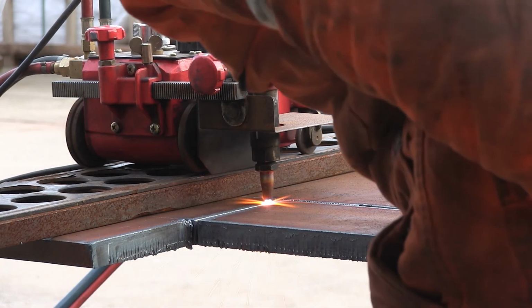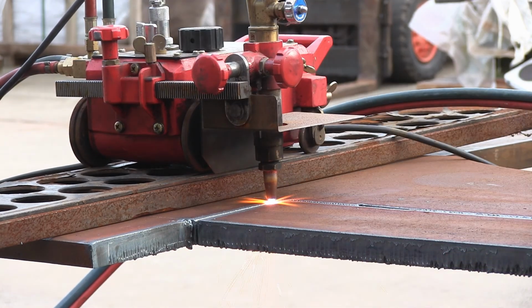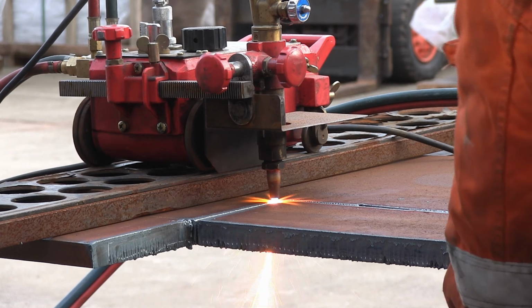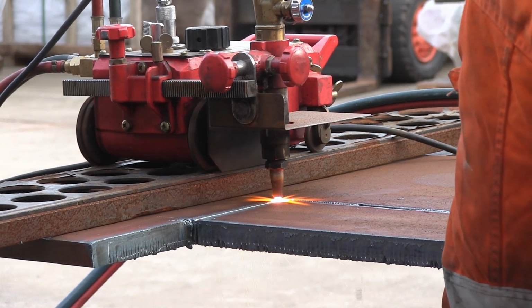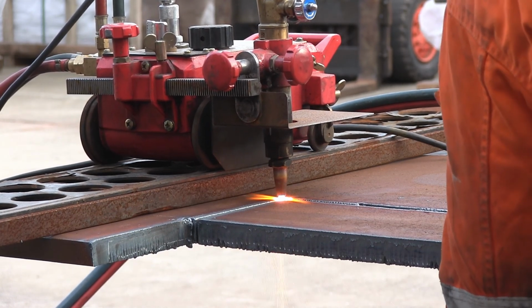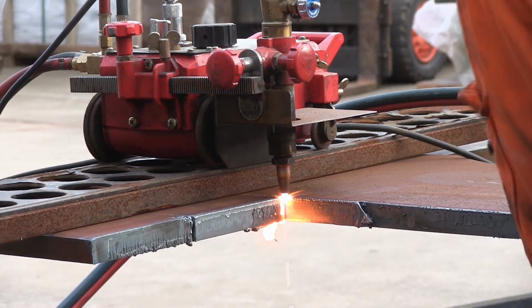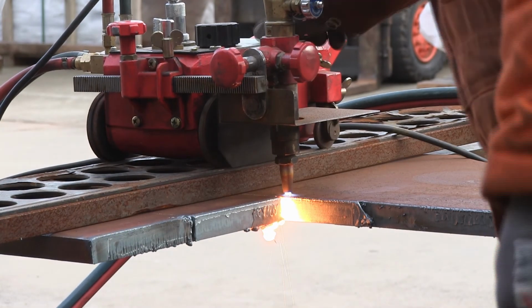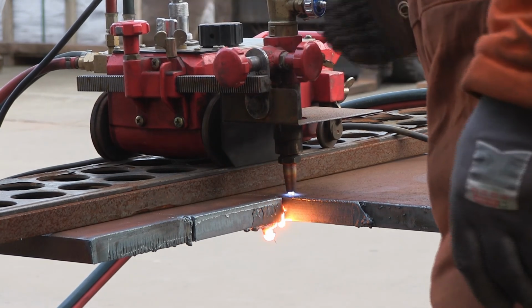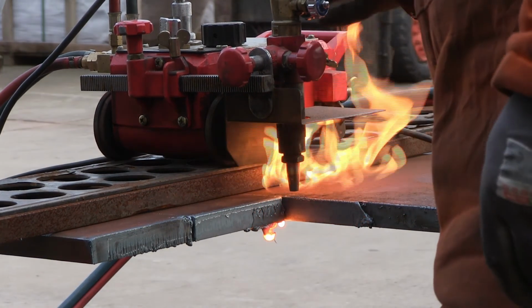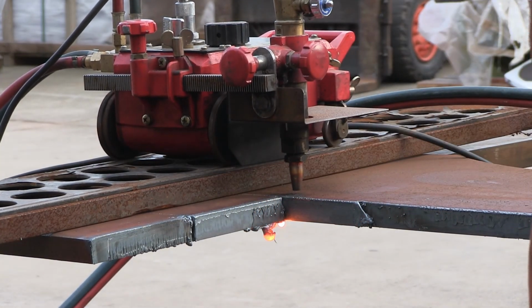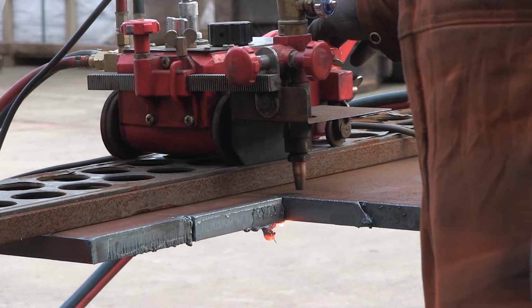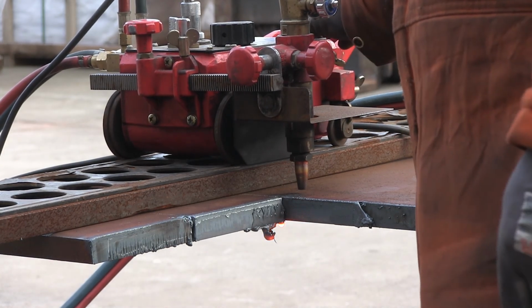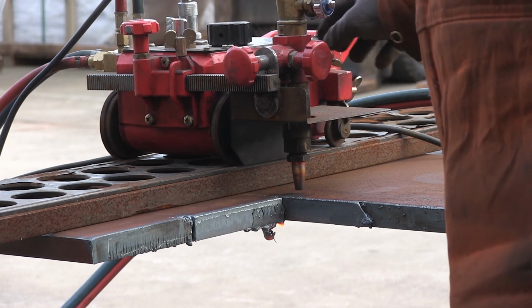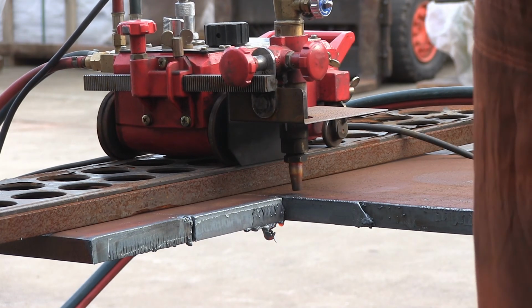Oxy-fuel cutting doesn't really like any laminations or dirt underneath, so the metal needs to be clean. And if you have some of them, sometimes you can see the puddle, the actual cutting jet getting swirled around, and that's the reason why it doesn't cut any further, because I stepped over a gap and there is no continuity. You need to start from a good temperature and start burning away; it cannot go between different parts.